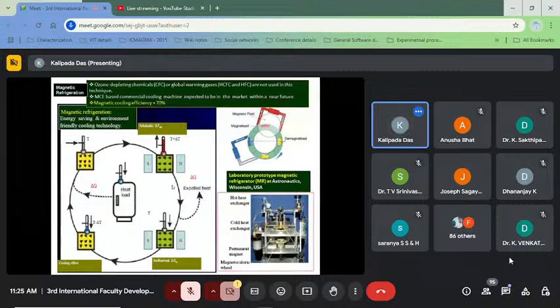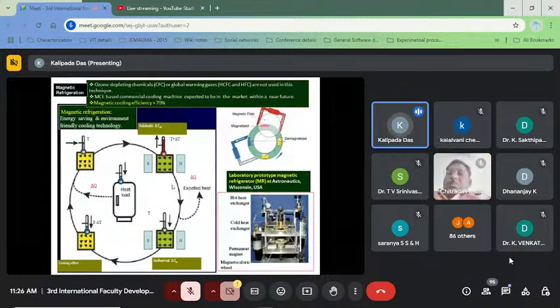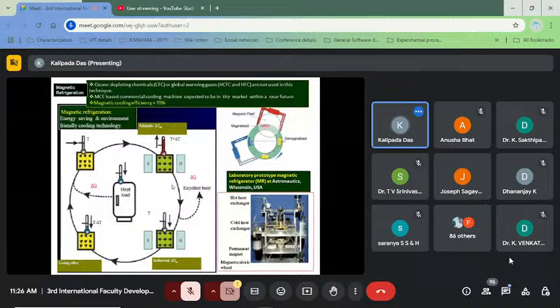Now, if it is isothermal with the environment, then it will expel heat delta Q amount, and it will again get temperature T, stable at that temperature. And now if we remove the magnetic field, then it will cool down to T minus delta T temperature. And if it is connected with the heat load at this stage, then it will extract heat delta Q from the heat load and get the environment temperature T. By this cycle, we can easily cool down any substance. This is called the magnetocaloric refrigeration cycle.